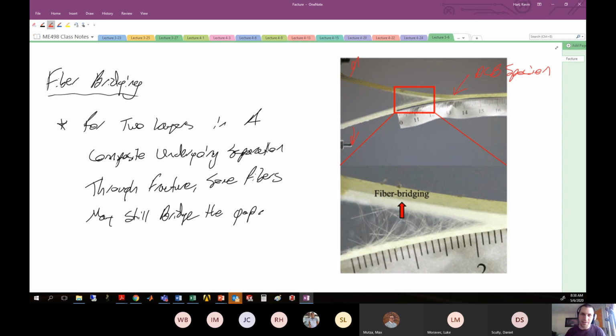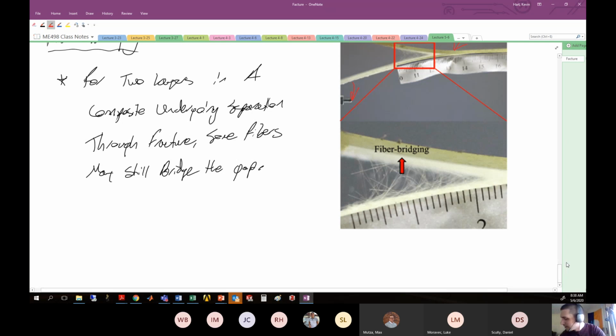The example that we have here is very extreme, and I think the people that were actually doing this test really made it a point to try to increase that fiber bridging by fluffing up the glass fiber mats that they were using to create this particular sample before manufacturing. So they really put a lot of effort into making this fiber bridging happen. But the general idea is there: when you pull open this composite, there are fibers that span this crack plane. So these fibers act to increase the toughness of the sample generally.